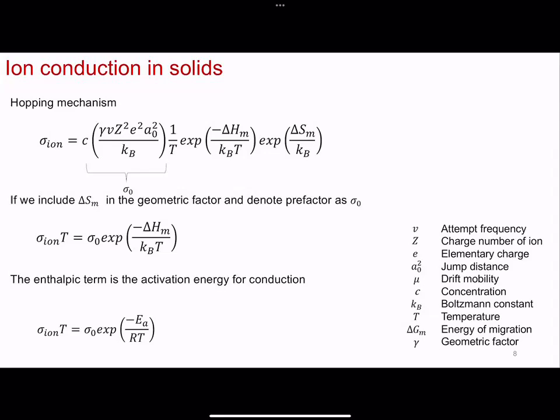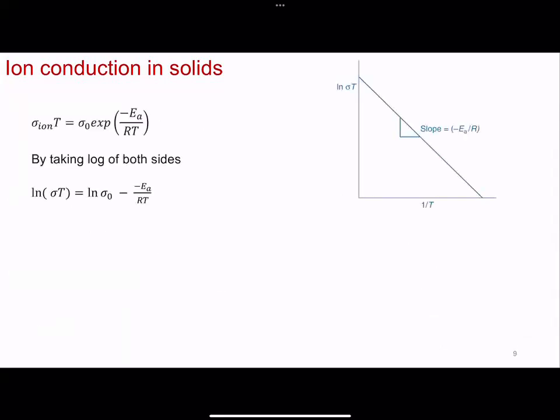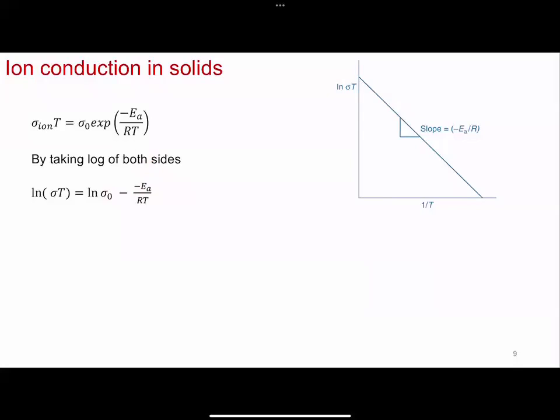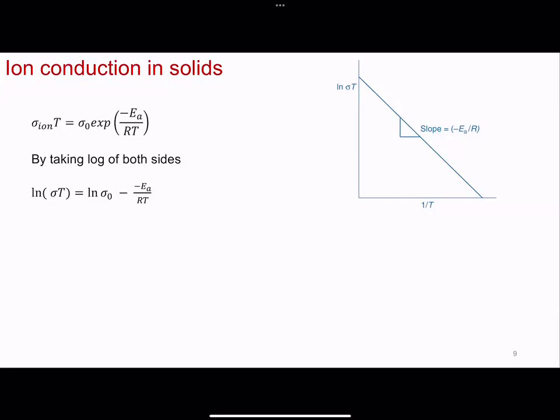So if you take the natural log of both sides, you get exactly that. Log of sigma T. Sigma is, now I've taken away the word ionic conductivity because I assume we're talking about ionic conductivity. So then if you plot log of sigma T as a function of inverse temperature, the slope will directly give you the activation energy divided by the gas constant. Simple enough. This is what you can typically get out of looking at these plots.